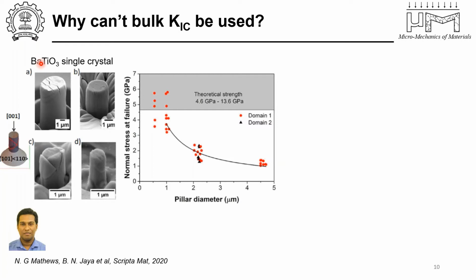For example, here what is shown is BaTiO3, a barium titanate single crystal. BaTiO3 is extensively used in piezoelectric and ferroelectric applications, which means it's used at small length scales in the form of thin films, and even as single crystals it's used in microelectronic devices. If I make pillars of this particular material and push them in compression, then I see that the yield strength of the material goes up and up, or what I call the failure stress keeps on increasing till it reaches near theoretical strength values.